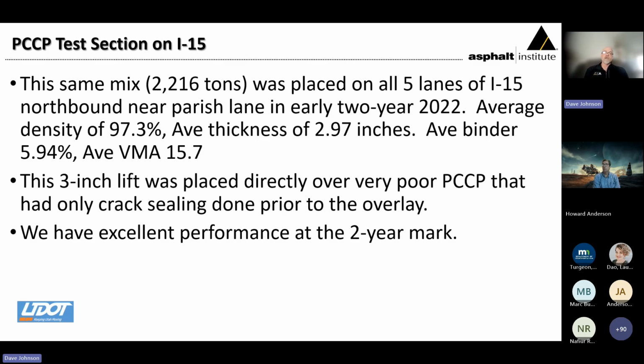It was a concrete pavement that had, quite frankly, performed as we would hope. It had given adequate service to the Utah DOT, but it was time to consider a change to that material. It had reached the end of its life. The plan had been, I believe, to crack and seat this material. And the decision was made, let's place some of this highly modified low air void material on it in a single 3-inch lift, and let's see how its performance is. And so that's indeed what was done.